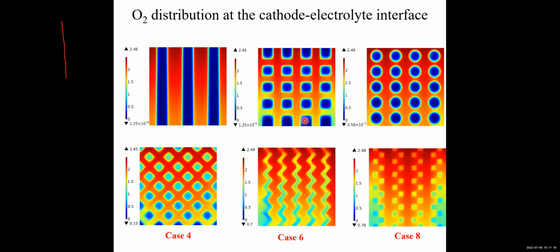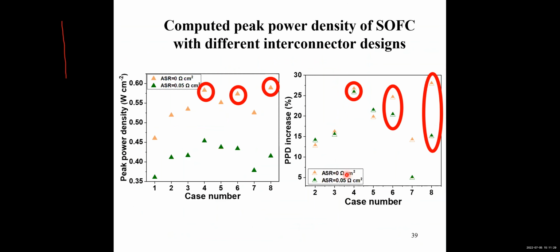So using different designs, we can improve the overall performance of the cell by simply designing different interconnector geometry. We found we can successfully improve the peak power density, with an increment of around 25% or even up to 30%.